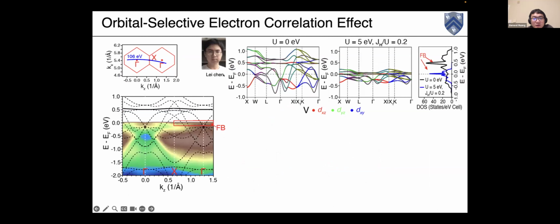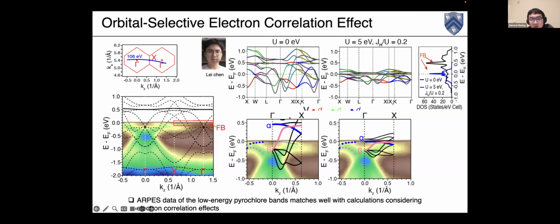So then Lei Chen, Qimao's student, did these calculations which include the correlation effect. So then the vanadium bands are strongly renormalized toward the Fermi level, and we compare these calculations with and without correlations to our data. We find that the calculation considering the correlation effect matched very well with the ARPES data. And in this case, the flat band actually shifts very close to the Fermi level.